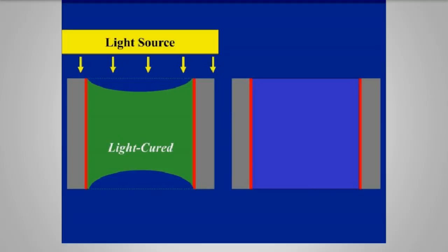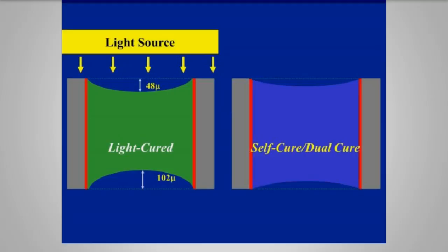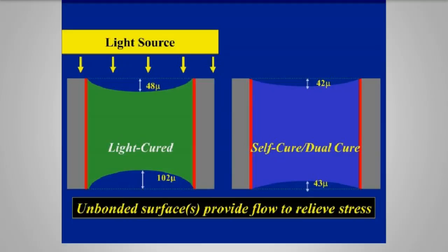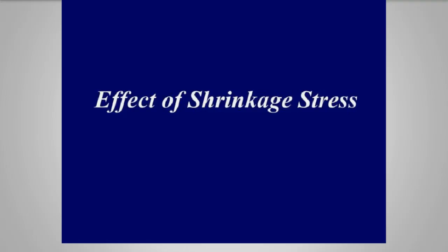So if you look at the schematic of light cured versus dual cure self-cure, the evidence does support that you're going to have less stress, especially in your adhesion layer, by doing that. So this is how the tooth relieves stress when you cure it. The stress comes out the occlusal portion here, and the larger the volume is on the class 1, the more the stress can come out. Where we get in trouble on the C factors are the small class 1s, where you have a very small opening portal to release the stresses. The relaxation by flow, less stress.